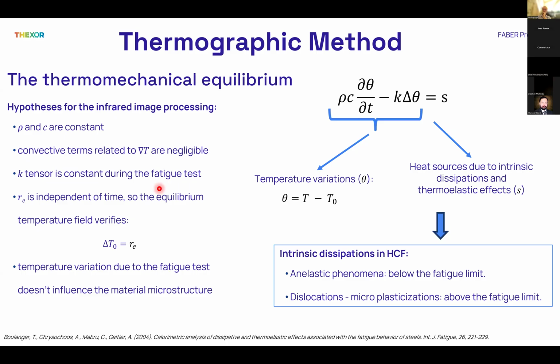This aims at satisfying the equilibrium temperature field reported here. The last hypothesis considers that temperature variation due to the fatigue test does not influence the material microstructure. So at the end, the thermomechanical equilibrium can be simplified considering just the temperature variations and its sources due to intrinsic dissipations and thermoelastic effects.